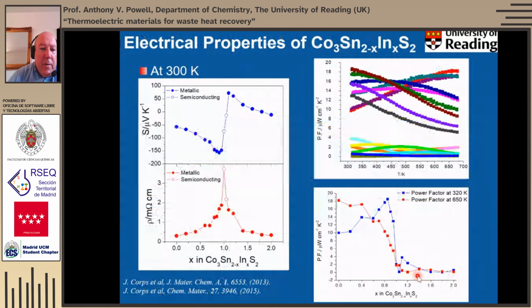So rather than showing all of the properties, I thought I'd just summarize really what's happening as we replace tin with indium here. What we find is that our Seebeck starts to increase as we move towards a more semiconducting region where the upper band is empty and the lower band is filled. Our resistivity also increases. And in fact, when we get to that 50-50 mixture of tin and indium, we do see at that point and just beyond, we do see semiconducting behavior, and then we come back out the other side and it becomes metallic. So this is quite an unusual example of a metal to semiconductor to metal double transition.